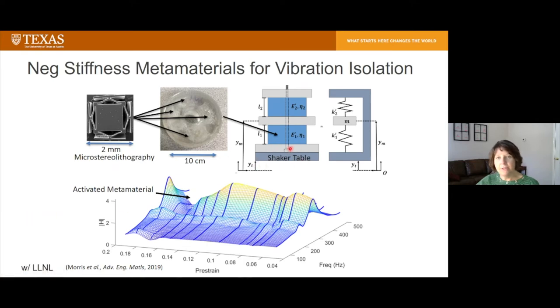The shaker table starts to shake, and then we can compare the acceleration at the shaker table to that at the top of the assembly. We also have a threaded rod moving through the center of the assembly, and so as we tighten that threaded rod, we pre-compress these beams. And so we get to the point where they're almost ready to snap through, but not quite. And that's a point where, as we start to vibrate the structure, they snap back and forth very violently, as violently as you can when you're only 2 millimeters large.